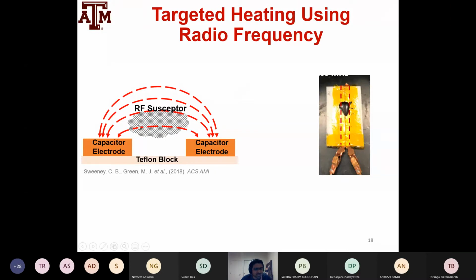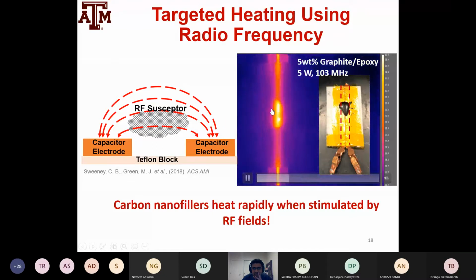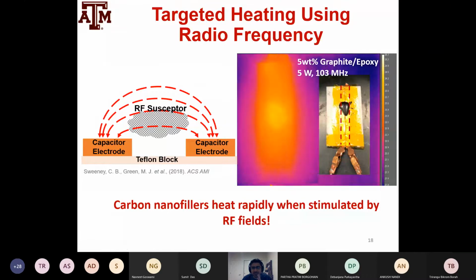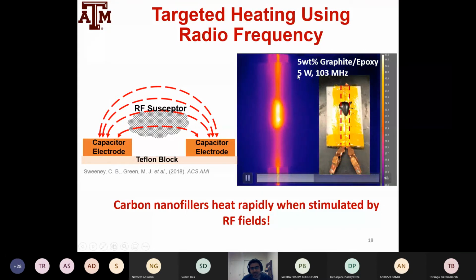What happens is that if you have this blob of material that has the correct conductivity, a very sweet spot, the material heats rapidly. Here you can see in this animation that we added 5wt% of graphite, and this is not even graphene, this is graphite, to simple epoxy, and we hit it with just 5 watts of RF power, and it heats really rapidly. Within a couple of seconds, it's able to get to 60 degrees Celsius.